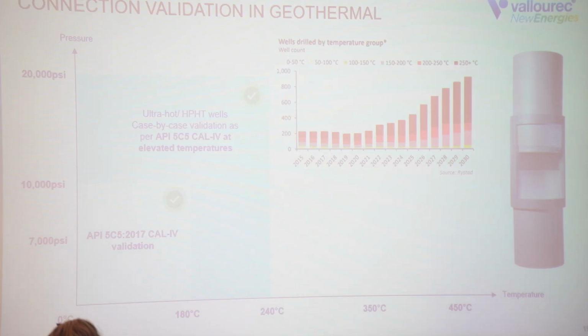So pretty much all the sizes were tested up to 180 degrees Celsius. For some projects, HPHT, it was tested up to around 240 degrees Celsius. But as you know, for oil and for geothermal, that's the split of the temperature for all the power generation geothermal wells that are expected. And as you can see, more than 2/3 of them will have temperature beyond 200 degrees Celsius. So it means the connection technology was not fully validated and suitable for geothermal.